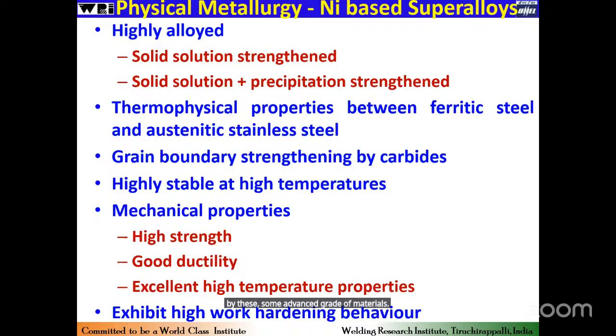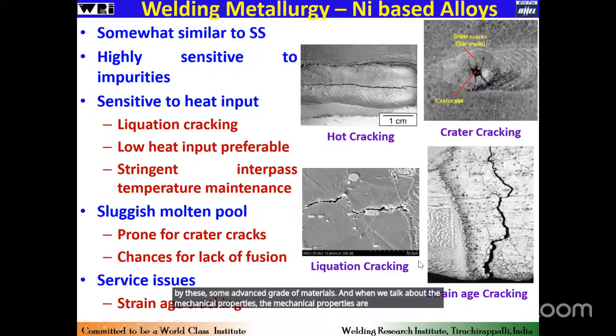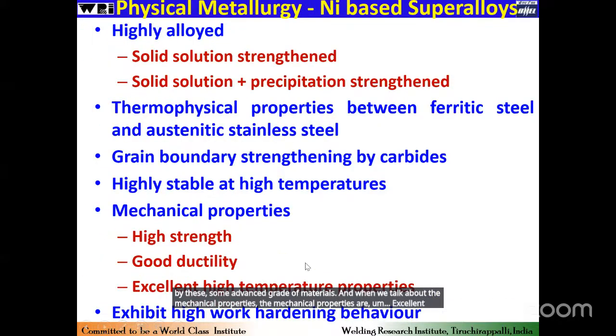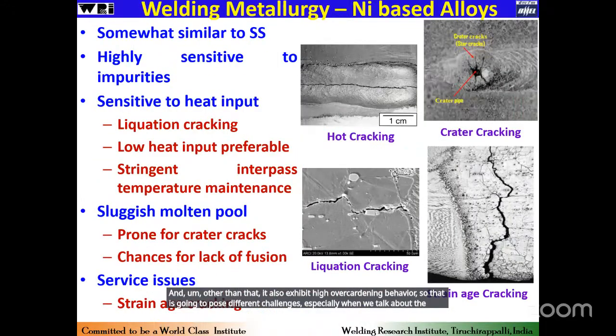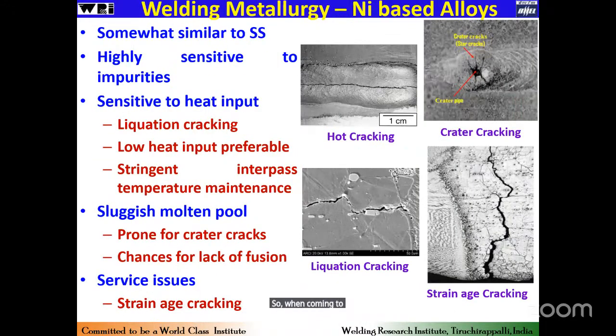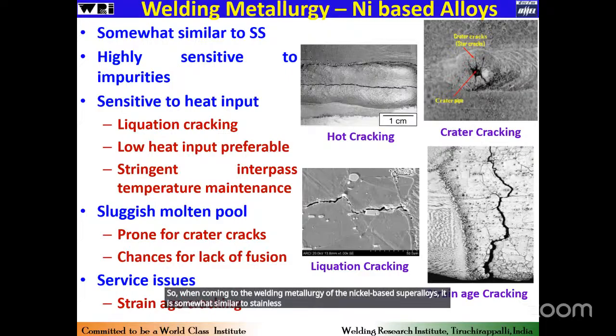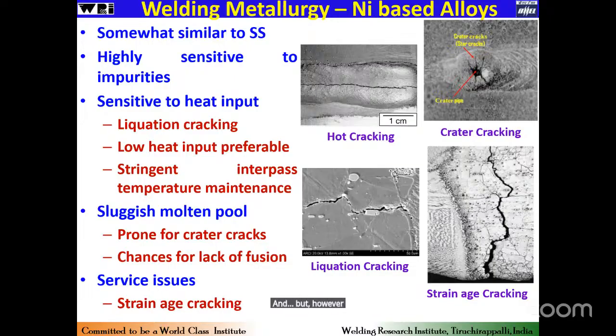And when we talk about the mechanical properties, they are excellent in terms of strength, ductility, and impact toughness. And other than that, it also exhibits high work hardening behavior. So that is going to pose different challenges, especially when we talk about the forming studies. So when coming to the welding metallurgy of the nickel-based superalloys, it is somewhat similar to stainless steel. When I say stainless steel, it is austenitic stainless steel. But however, it is highly sensitive to impurities.